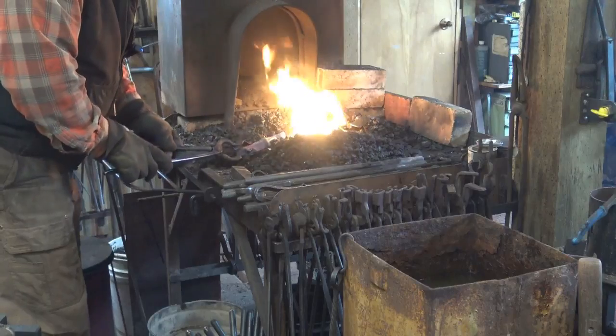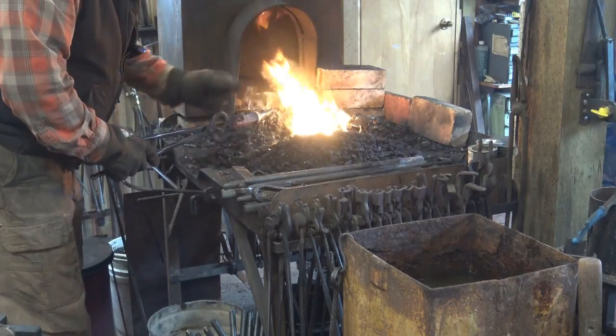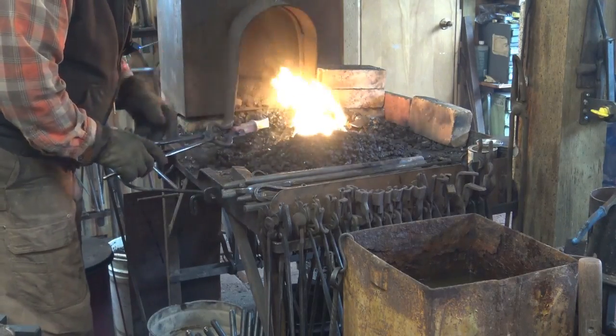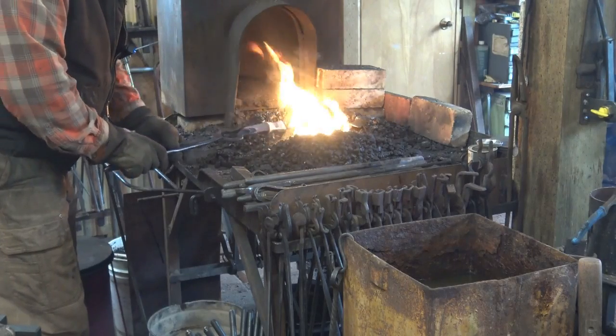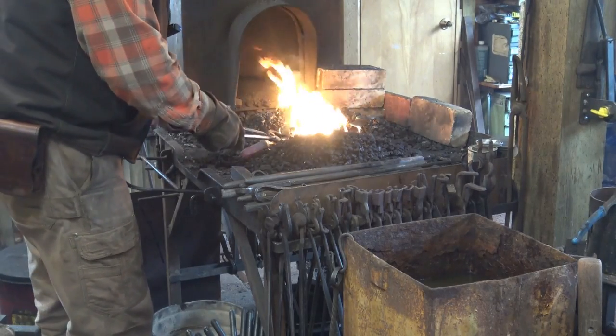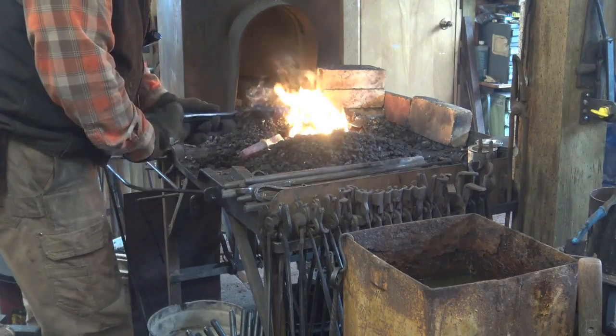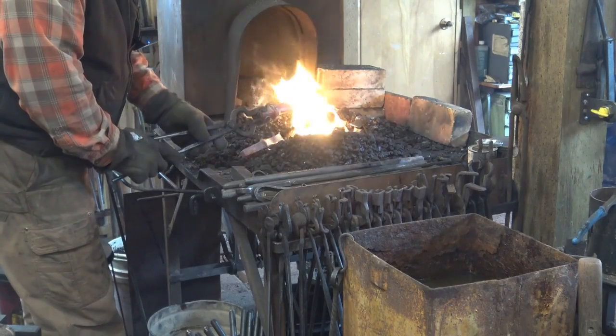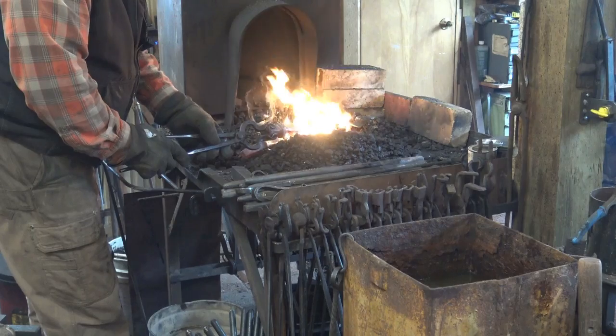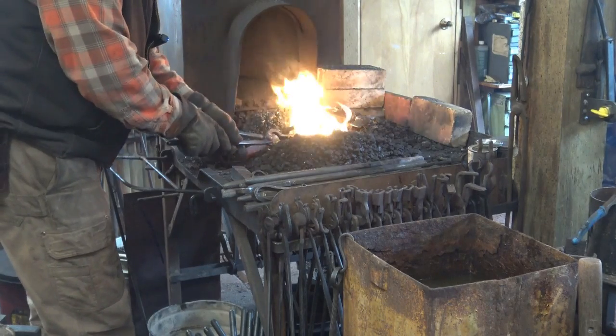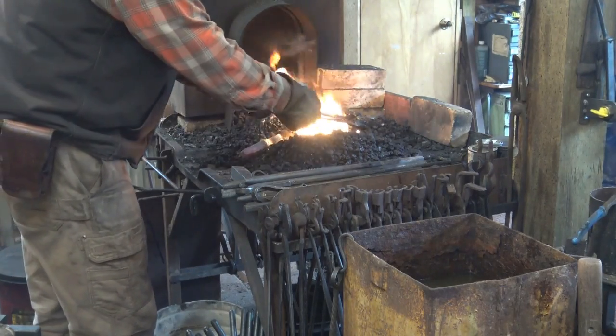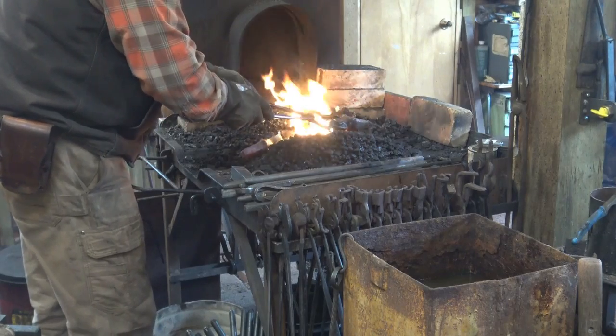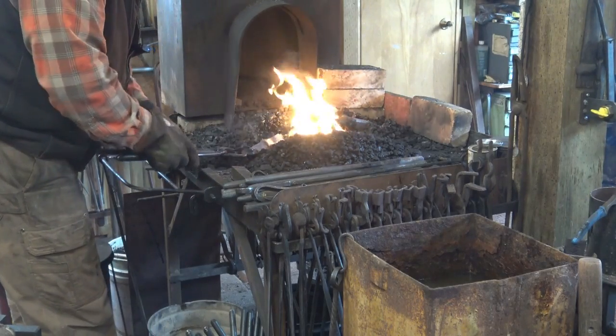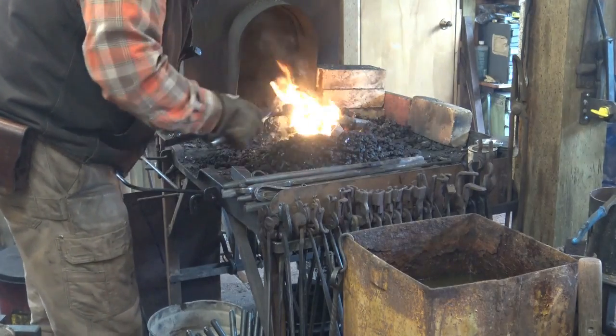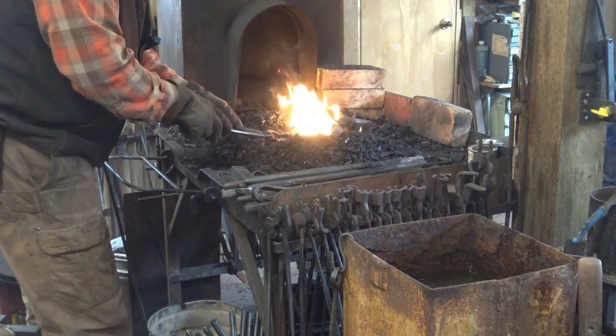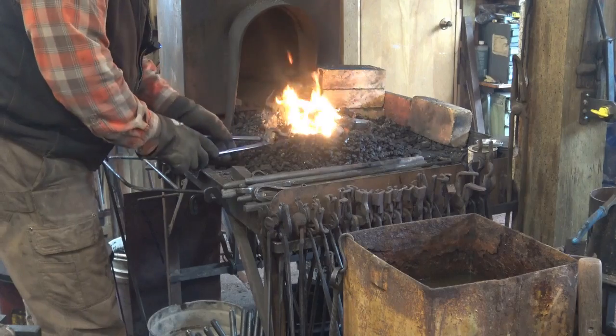Now I've let these sit and come up to temperature, and some of them, the hardy stems, because that's what I had in there, are just starting to glow, so they're a little higher than that 1200 degrees. And I'm going to put the one we're doing in water, the jackhammer bit that I presume is S2, and that's actually in the fire. The other two I've pulled out to the edges where they'll stay hot, but they won't come up in temperature any. And I'll do one at a time at this point.